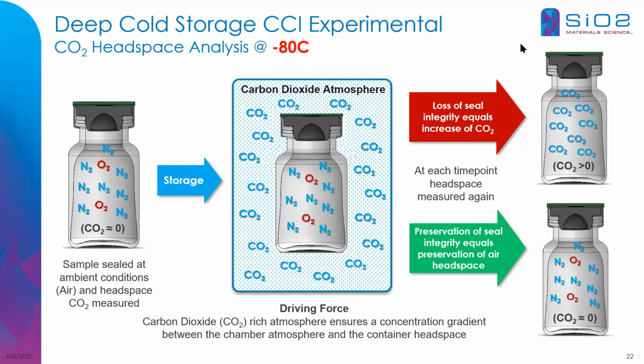We then put it into a chamber filled with carbon dioxide. That provides the driving force of gas that could permeate into the container. And then we lower the temperature to -80 and hold it at that temperature. It's a non-destructive test where we can measure the change in concentration of CO2 within the container over time. And if you see the ratio of carbon dioxide going up in the container, that's a function of leakage.